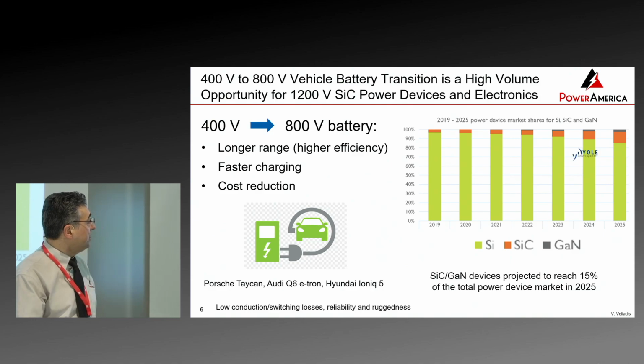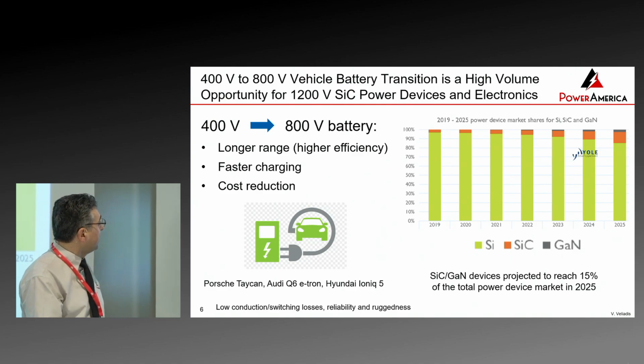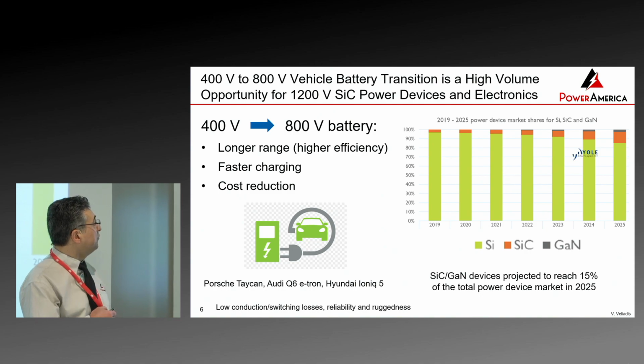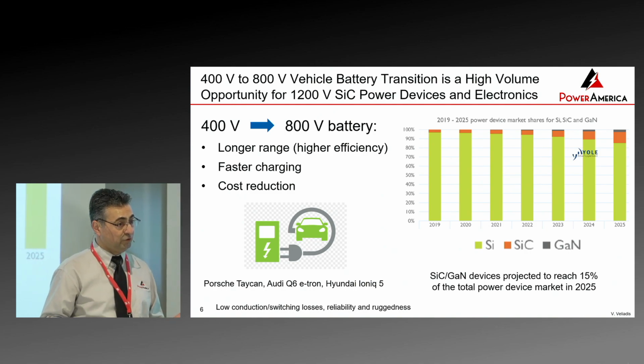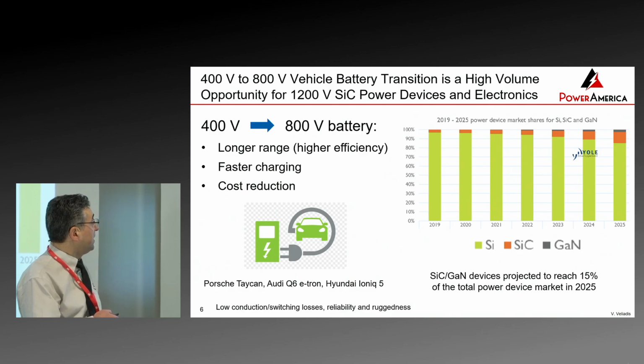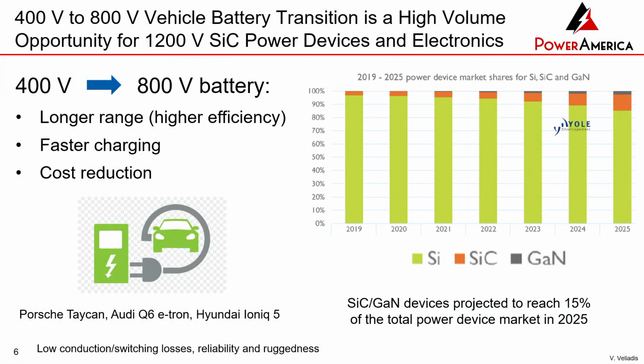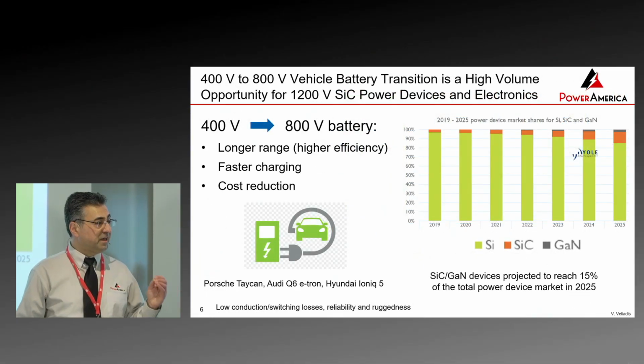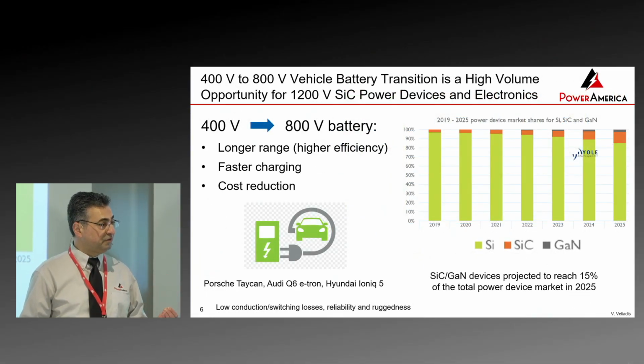Now, one key item that's happening in electric vehicles is we're moving from the 400 volt bus to the 800 volt bus. And why are we doing that? It's higher efficiency, so you get longer range. You can do faster charging and cost reduction. There's this graph from Yole, and we'll hear from them tomorrow in detail. But you can see that silicon carbide and GaN in the power market are about 15% or even more. And that's a really, really big application, because as you move higher in voltage, that's where silicon carbide and GaN become more competitive compared to silicon.